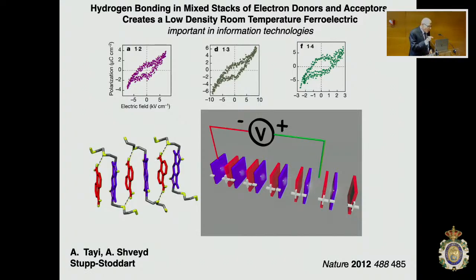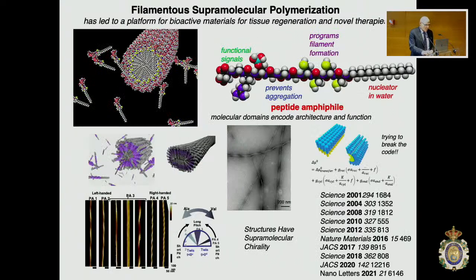And it is that bond, precisely, that created a ferroelectric material at room temperature. So in Japan, a group at the University of Tokyo had discovered that they could mix molecules like this and create ferroelectrics, but the ferroelectricity was only possible at 85 degrees Kelvin, which of course would make it meaningless in a technological context. And that simple hydrogen bond stabilized the ferroelectricity all the way up to room temperature. So this was an important thing.